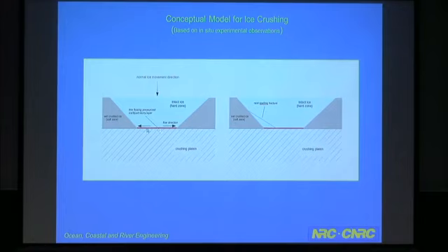In other words, the slurry layer, due to its viscosity during the flow, melts that ice and also erodes it. And I'll get into more detail on the erosion a bit later. But that slurry plays an extremely important role in ice crushing. And we'll talk quite a bit more about that. So that's the essentials of the process.